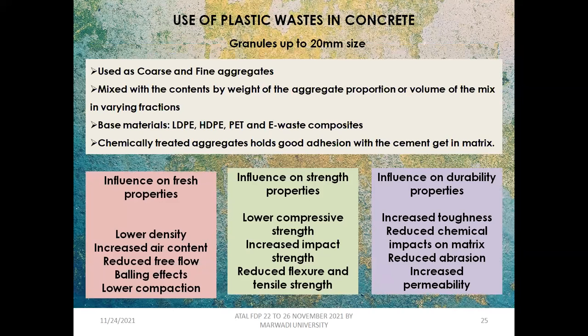So granules, when we talk about a rough size of up to 20 mm or an average size, with the base material of LDPE. Fortunately, we are in a city where all the industrial facilities are available, where plenty of recycling activities take place. So we were fortunate enough to have a variety of recycled plastics from a variety of base materials like LDPE, HDPE, PET, and e-waste also. Chemically treated aggregates hold good adhesion with the cement gel in the matrix. Then they can be used as coarse and fine aggregate, so there is flexibility. These are some of the overall observations I have come across while using plastic as granules